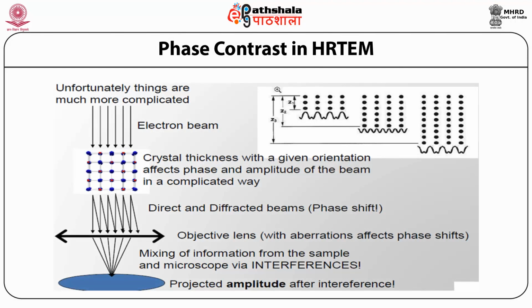Phase contrast in Hrtem, crystal thickness with a given orientation affects phase and amplitude of the beam in a complicated way, and direct and diffracted beam has a phase shift. With that, mixing of information from the sample and microscope was via interference will develop a high resolution image, and a projected amplitude after interference will get the final output.